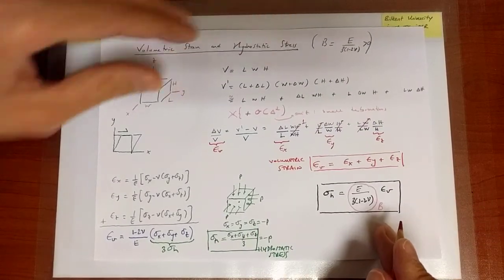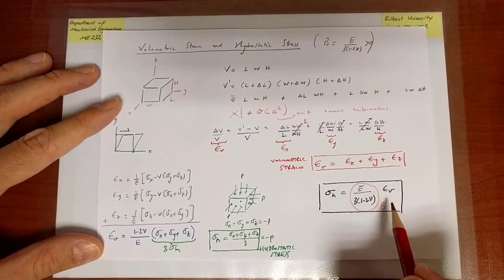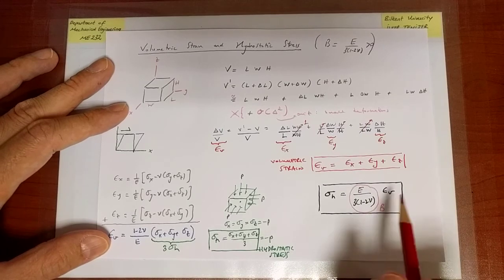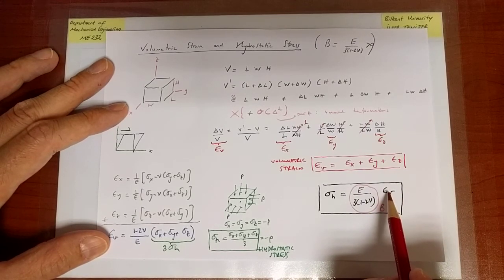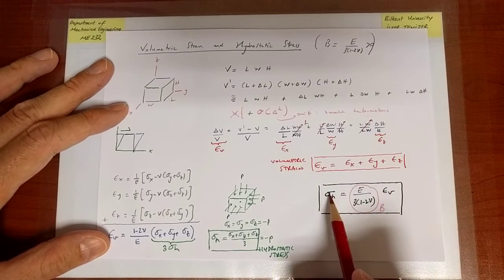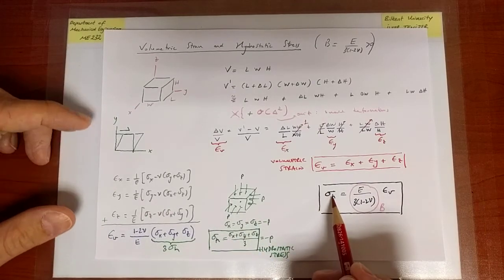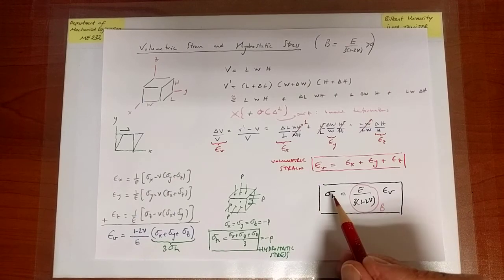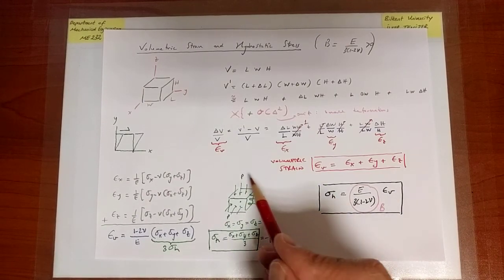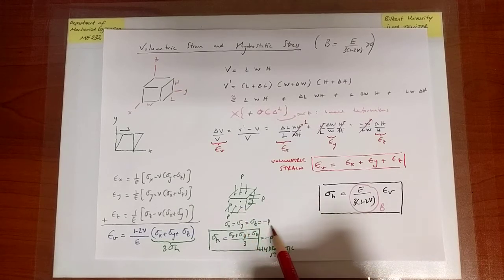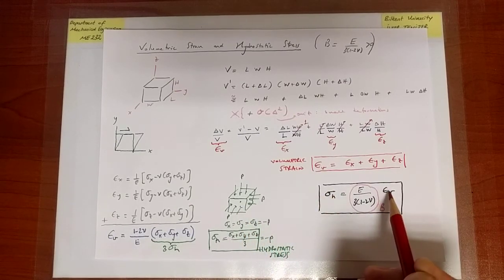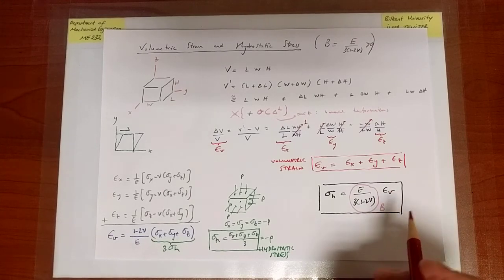And here is the motivation behind it being strictly positive. Because if I want to induce a positive volume change, I better have positive normal stresses on the cube, or in this case, the sum of the stresses. Here the hydrostatic stress is going to be minus P, so it's going to be negative. Volume change is expected to be negative as well, and B, therefore, better be positive.